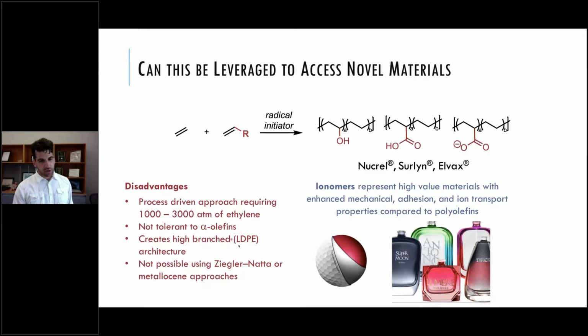It creates a linear low or a low density polyethylene architecture, and essentially you can't use Ziegler-Natta catalysis to do this. You have to use these really special conditions where you're pressurizing these reactors to 1,000 to 3,000 atmospheres of ethylene pressure. So this is a really specialized process-driven approach to make these materials. We want to make these high-value materials not by using thousands of atmospheres of ethylene. We want to make them from waste.